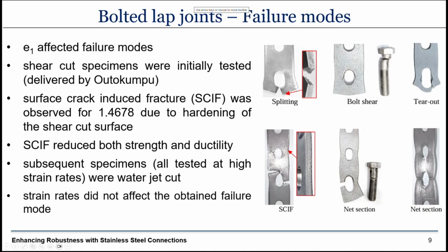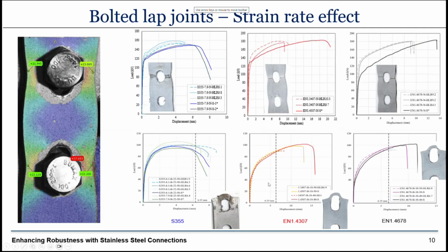We did similar tests on both static and high strain rate lap joints. The strain rates did not affect significantly the obtained failure mode. The failure mode was more or less identical, but for higher strain rate, failure occurred at smaller overall deformations without affecting the failure mode. Here, we can see some selected results. On the left-hand side, we see the carbon steel specimens. So top left is net section fracture, bottom left is shear out at the bolt hole, so like bearing failure.